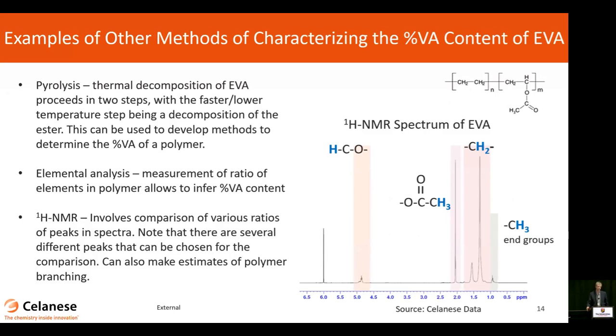There are other ways to characterize vinyl acetate, ranging from challenging and esoteric to, I think, more routine. Obviously, pyrolysis is a practical method you can use. It's actually a very challenging method in practice. But in this case, you degrade the ester, right? So you heat up the polymer to a temperature where the ester decomposes, and you can characterize weight loss, or you could attempt to capture the acetic acid that's generated and titrate it. So that is a method that's been used.